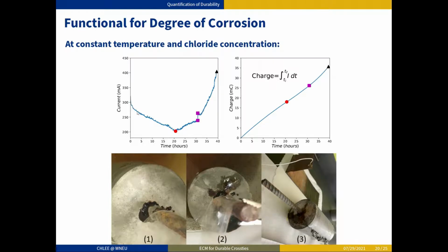So when the current is at its minimum, you can see the leakage of the corroded products, and then you can see the current jump from one level to the other. That is the point where you can observe the slight hairline cracks on the surface of the concrete. And then when we observed the longitudinal splitting crack, we stopped the experiment. However, the current level is quite a bit higher than the initial stage. Accordingly, if you integrate the measured current, you get the right panel curve like this.